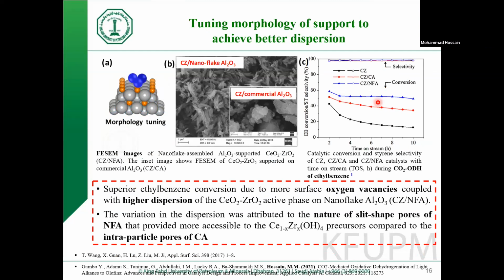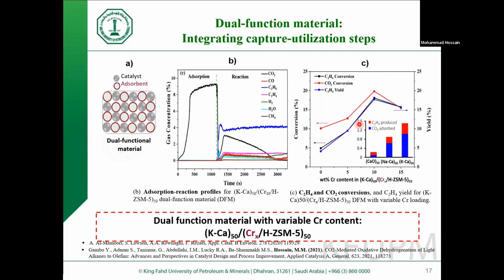The morphology can also be adjusted. This example shows the dispersion of ceria-zirconia on aluminum nanoflake. And in this case, the support was varied. One can see here this blue line: adjusting the morphology helps a good dispersion of ceria-zirconia, that has been reflected with a stable conversion and product selectivity.